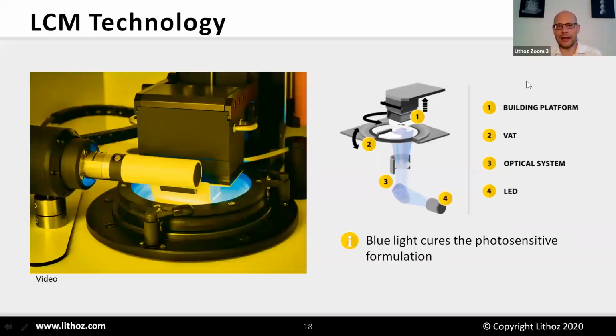I'll show you here the video of how it works. You can see now the movement, it moves down. It exposes everything at once, for a couple of seconds, moving up again. Then we have the recoating. We are recoating the layer, moving down again, exposing with blue light, and finished. So this is how layer is built upon layer. There are also some YouTube videos available for more details. But what you have to bear in mind is that we have a mask exposure and we are building upside down. So we are pulling the part out of the slurry, which has very good advantages because you are using very little material. Even for mass production, you can save a lot of inventory and have a very efficient and effective process.